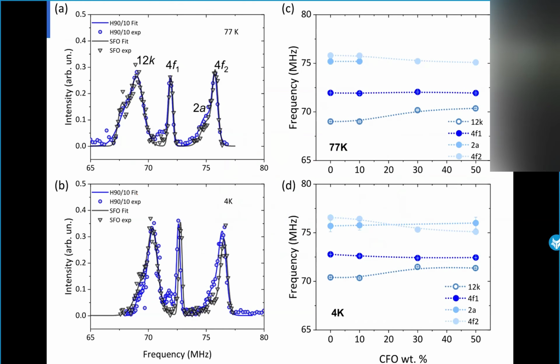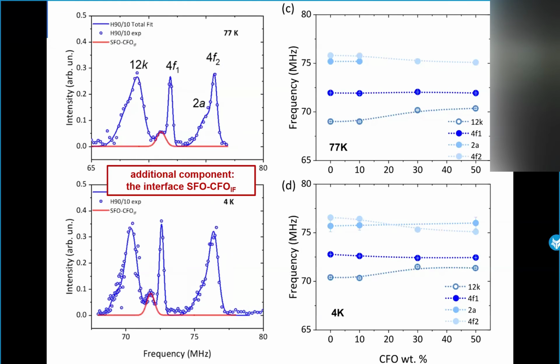Not only is there a change, but if you compare, for instance, the pure SFO with a 10% CFO sample, here you see an extra peak emerging, which is exactly the extra peak that Nader was mentioning this morning. So I would like to stress that this peak is here, enlightened by the red line, and this is the additional component that Nader has already talked about, observed also by Mössbauer, which is the additional component due to the interface between the SFO and the CFO.